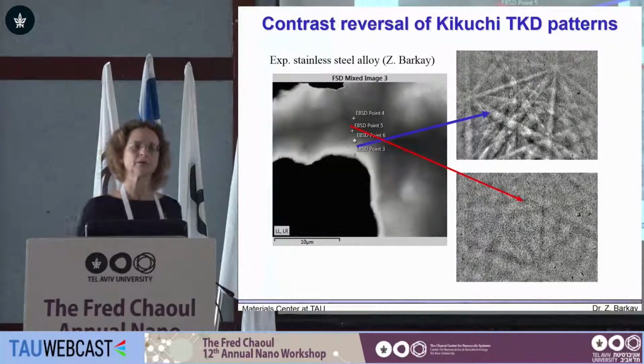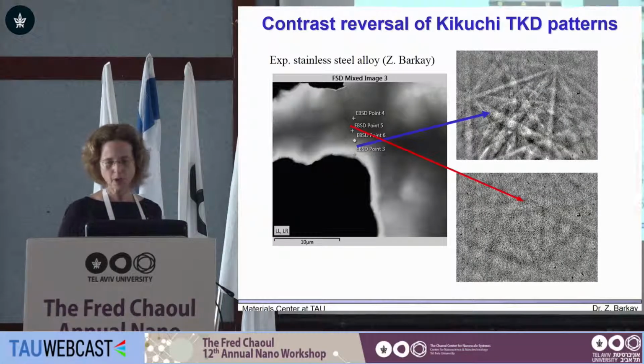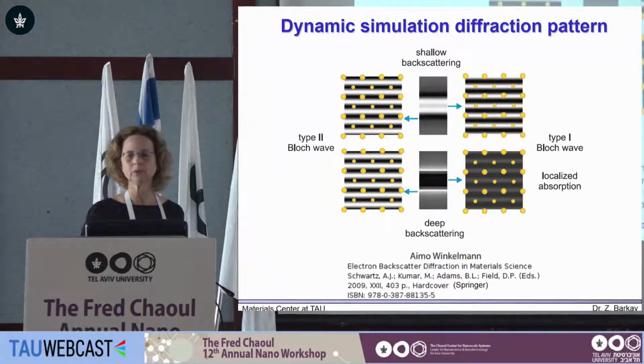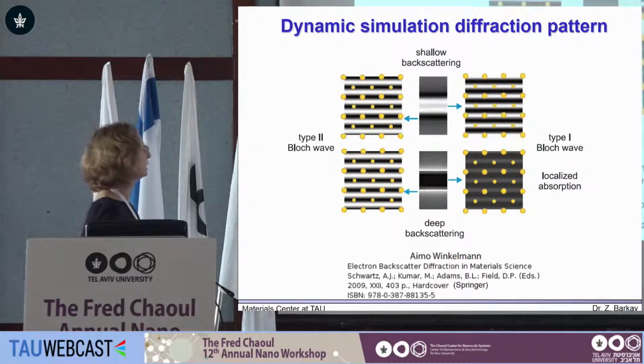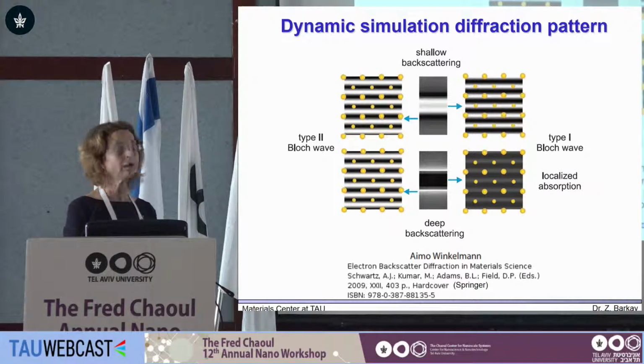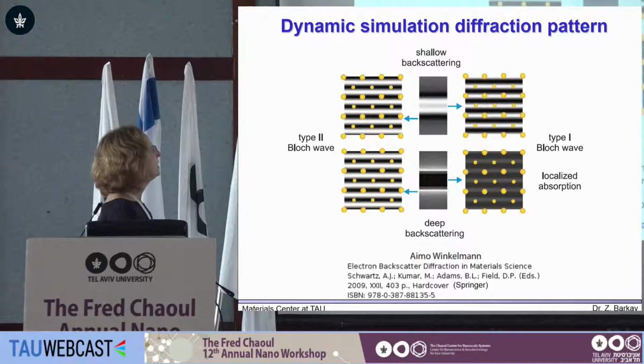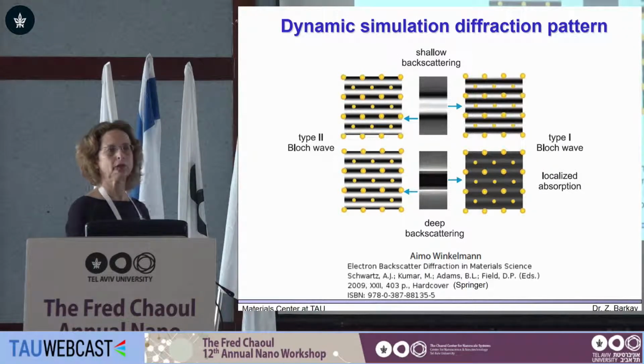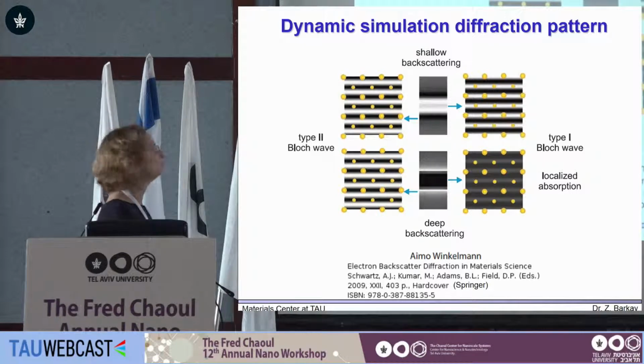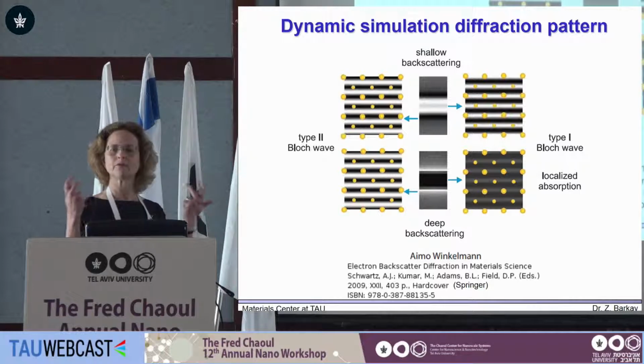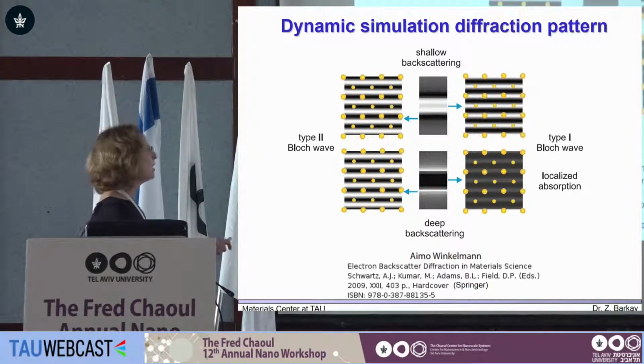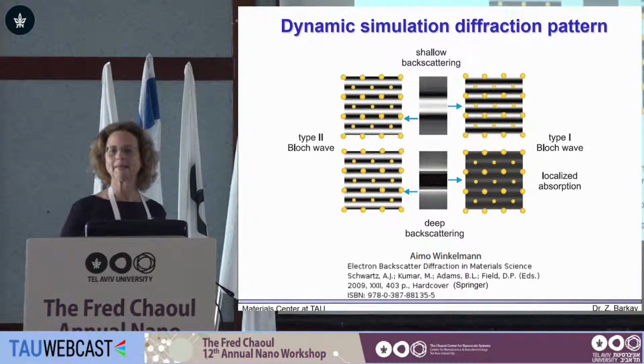It also occurs in reflection, and it's very interesting to show how it was simulated in order to understand what is happening. This simulation was done by Aimo Winkelmann, a very nice simulation taking dynamic diffraction into account. What he actually showed is that the regular pattern we obtain is a superposition of type 2 and type 1 Bloch waves. Type 1, as you remember from solid state physics, is for electrons going on the planes, and type 2 for electrons going in between planes. This superposition is what gives us this contrast.